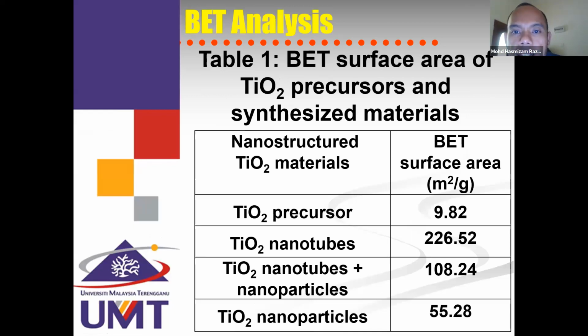So we carry out the surface analysis of the synthesized sample. Using the BET analysis for the titanium dioxide precursor, the commercial TiO2, we observe 9.82 meter square per gram. For titanium dioxide nanotube, which is the sample we obtain after calcination at 400 degrees C, the surface area is 226.52 meters square per gram.